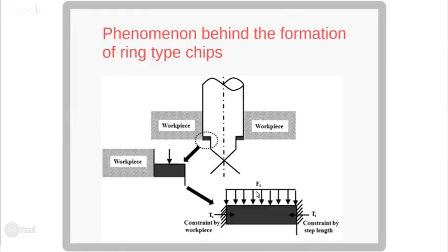Okay, as there is a lot of temperature, heat generated on the surface of this one. Okay, as the base is aluminum, the coefficient of expansion is very high. Now, temperature stresses are generated on the last flake of the material. Because of these temperature stresses, the stresses are acting in this direction.